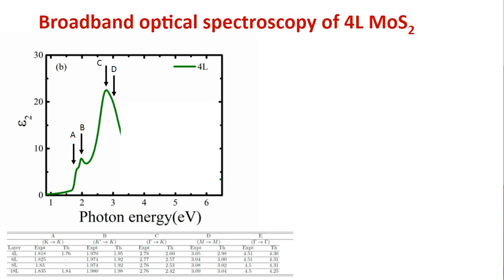So we immediately thought of the idea of extending our data to beyond these A, B, C, D excitons. But that meant that we have to use a broadband spectrometer rather than this 1 to 3 eV spectrometer, because a lot of this data that is published in the literature were obtained using ellipsometry. Ellipsometry is another technique, but most of the commercial ellipsometers are limited to about 3.2 eV. But because we had the Shimadzu spectrometer, which would go to 6 eV, we immediately thought of a project of measuring the broadband optical spectroscopy of the 4-layer MoS2.